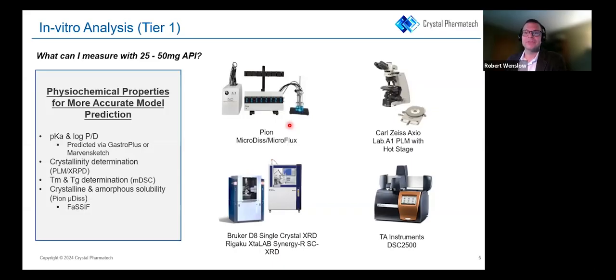Get a DSC, but don't just do a standard DSC. Do some cycle experiments. Get a modulated DSC. Get the most bang for your buck, getting a glass transition temperature, a melting point. You can even use those values from the DSC to predict an amorphous solubility.